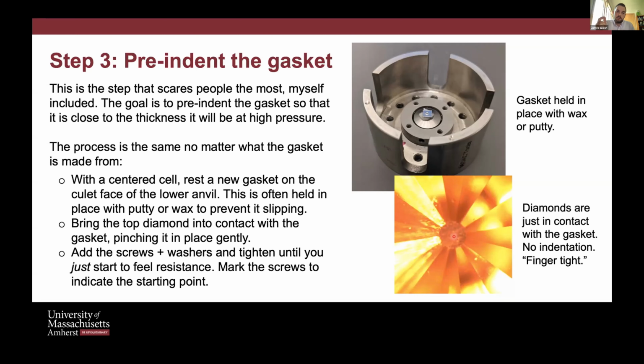Typically we'll tighten the screws, not fully, but just enough so that there's some give, and that's what we say is the beginning. We typically will mark the screws. You put a Sharpie over the screw head, a line that starts on the screw head and onto the cell, and that says 0 degrees. That's where you started from. That's important because there is some repeatability to these cells. If you take notes and you see that for this indentation thickness, I turned 2/3 of a full turn, you'll probably find, as long as everything else stays the same, that you can just use that in future. So it's worth making notes on these things because they are repeatable for a given cell. So that's where you start from.